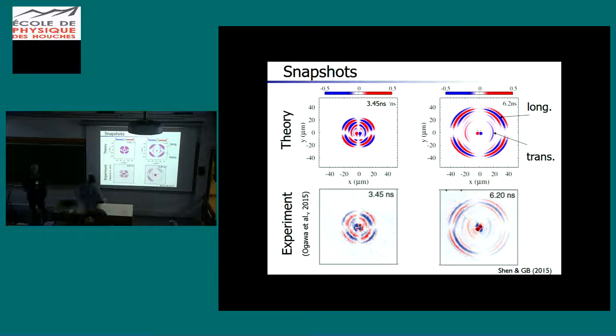So the lower ones are the transverse ones. So we see they have different phase velocities and different group velocities. Now the group velocities are exactly the sound velocities. So what we see here are the phonons. They are expanding, and because of the phonons you have these magnetoelastic effective magnetic fields which excite the magnetization. So the magnetization, what you see here, is basically the phonons.